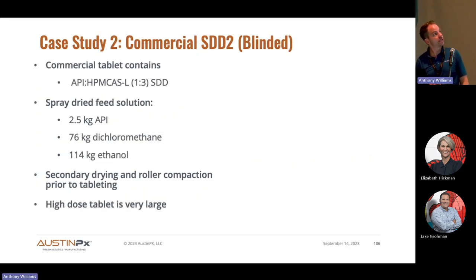Now on to case study 2, and this is the subject of some fairly recent research, so we blinded it for now. We'll make it public soon. But the commercial product contains the API in HPMCAS, once again in a 1:3 ratio. Similarly, the feed solution to spray drying contains quite a bit of chlorinated solvent and ethanol and a fairly low solids load. So it's very costly in terms of spray drying, with a lot of drying time and a lot of solvent waste to obtain relatively little amounts of API equivalent.